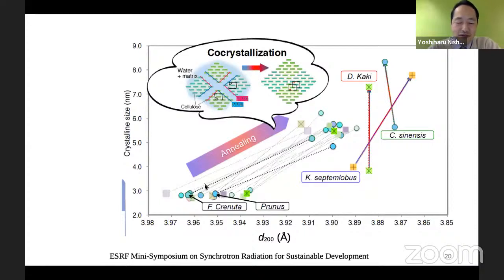What happens during the annealing from room temperature to 200 degrees is that somehow the crystallite size, which we can evaluate from the sharpening of the peak, increases, and we have a packing that becomes slightly different, that we interpret in this way. In the beginning, inside the intact wood, we have water and matrix surrounding very thin crystalline microfibrils, and during the annealing close to 200 degrees, we have this tight packing between the neighboring crystals that expels the matrix component from between the crystallites.